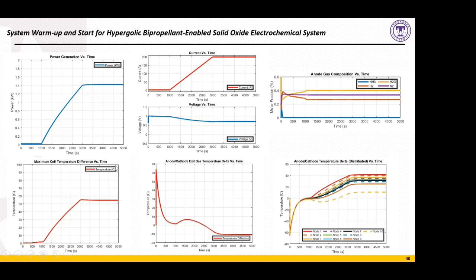And by doing this, we can minimize the temperature difference across the cell, basically the maximum temperature minus the minimum temperature. We also shrink down the delta between temperatures at a given node, and these nodes are taken crosswise across the stack face. And then we also reduce the differential between the anode and the cathode exit gases or exhaust gases.